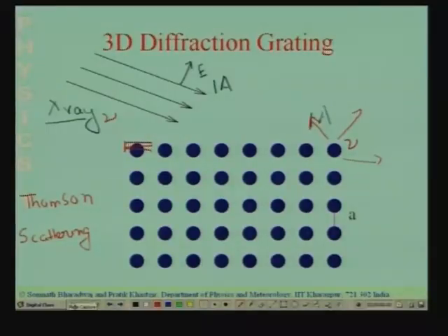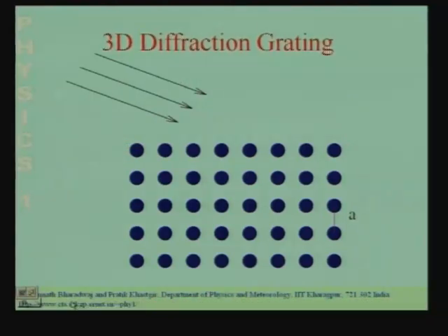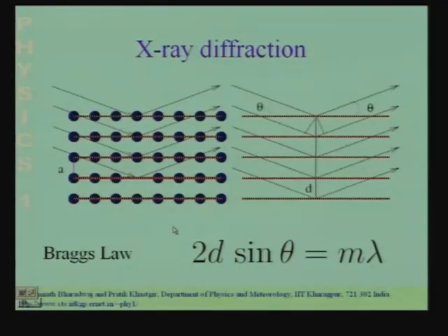So, you are going to have this radiation coming out, and to determine the intensity pattern in different directions, you have to add up the radiation from this periodic arrangement of sources. And we have seen that if you have a periodic arrangement of sources all radiating coherent radiation, then you are going to get a diffraction pattern. So, what we have over here is an X-ray diffraction pattern that is going to be produced by the radiation from this periodic arrangement of sources.